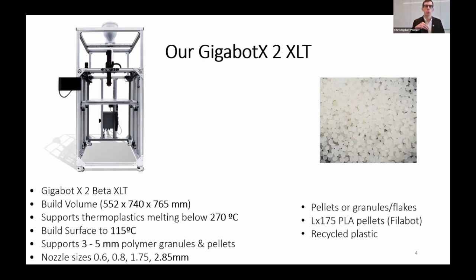So you're skipping the filament making step when you print from pellets, granules, or flakes. This machine supports a range of nozzle sizes. And in this talk, we're going to use 2.85. So you might think of 1.75 as a common filament diameter, or even 2.85 is a very thick filament diameter. We're using 2.85 to make the beads on this machine for the work that you'll see here. And then we can also go to a more traditional, like a 0.6 millimeter nozzle.